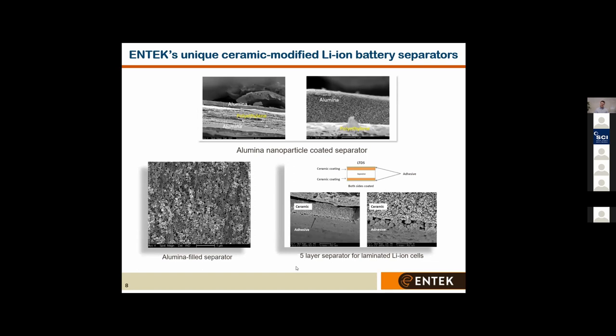So looking at the unique ceramic modified separators that we make, I think you can see from these SEMs that ENTEK is a proponent of double side coated, both ceramic and adhesive coated separators. If we look at that upper image, you can see it's a double side nanostructured alumina coated on the polyethylene, approximately 1.5 microns thickness each side. And really that's primarily for cylindrical cell applications. The lower right is a 5-layer double side ceramic and PVDF coated separator, predominantly for laminate pouch cell applications. The bottom left image is a unique product that we make, and it's an alumina-filled separator where the nanoalumina is interspersed within the skeletal structure of the polyethylene microfibrils.